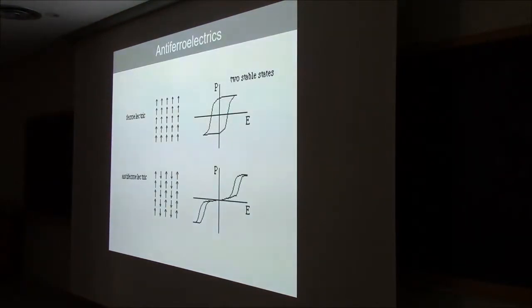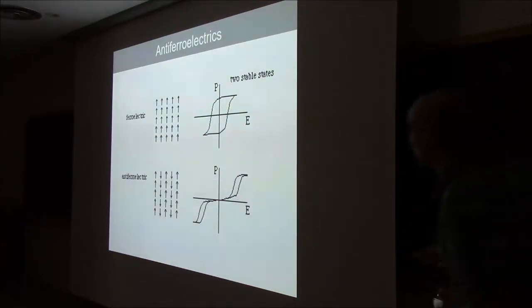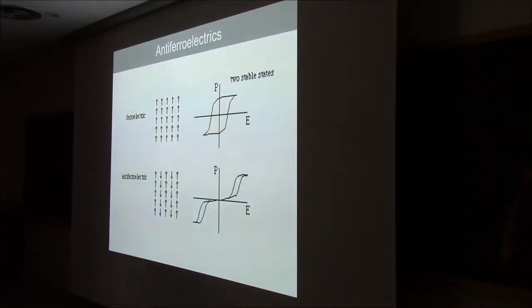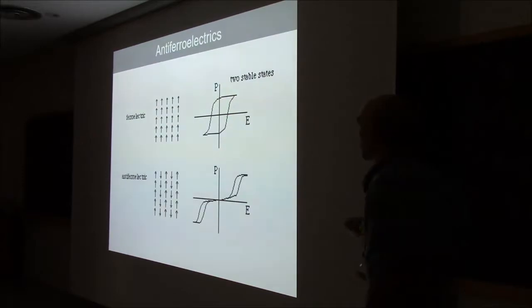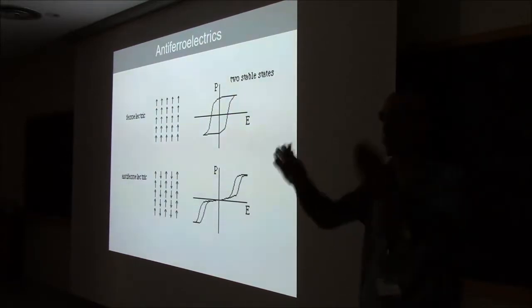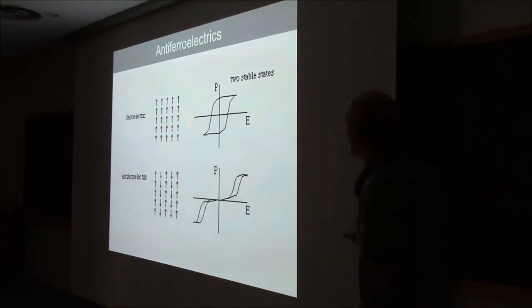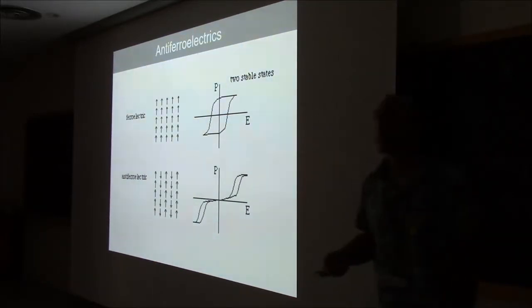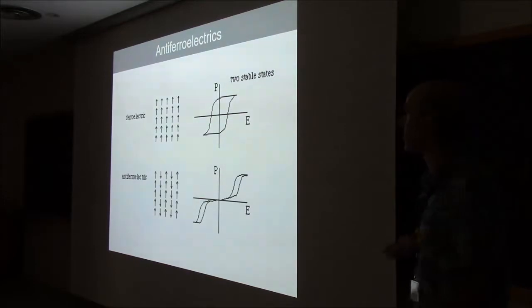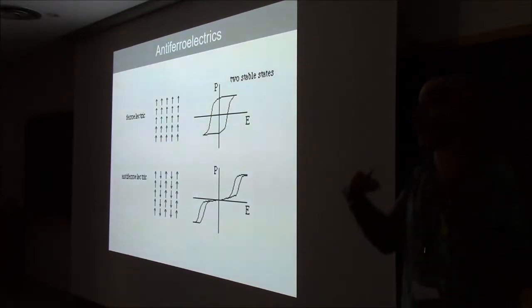So that's the second family of almost ferroelectric materials. This is yet a third family of materials that are very closely related to ferroelectrics, but they are not. They are anti-ferroelectrics. In a ferroelectric, you have all your dipoles, permanent, stable, pointing in the same direction, and you can switch them with an electric field, and you have the typical polarization versus field hysteresis loop. In an anti-ferroelectric, you can think of it as having these dipoles aligned anti-parallel to each other, as you would in an anti-ferromagnet.